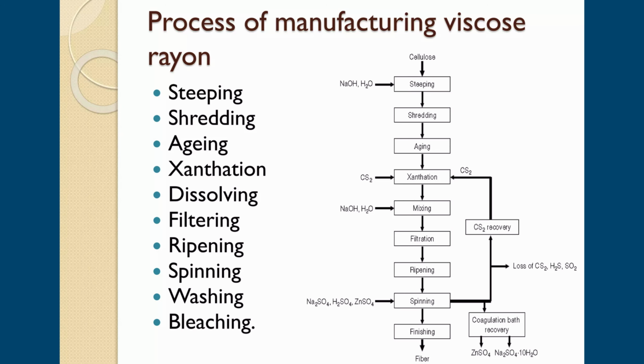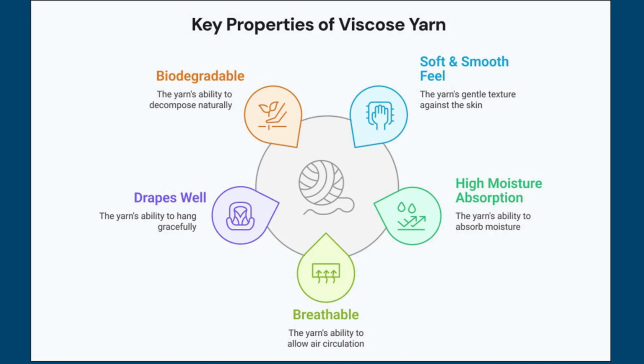The viscose solution is filtered, degassed, and extruded through spinnerets into sulfuric acid, where cellulose is regenerated and the xanthate groups are removed. The resulting fibers undergo washing, bleaching, stretching, and finishing. Viscose rayon exhibits excellent softness, high moisture regain, outstanding dyeability, silk-like drape, relatively low wet strength.